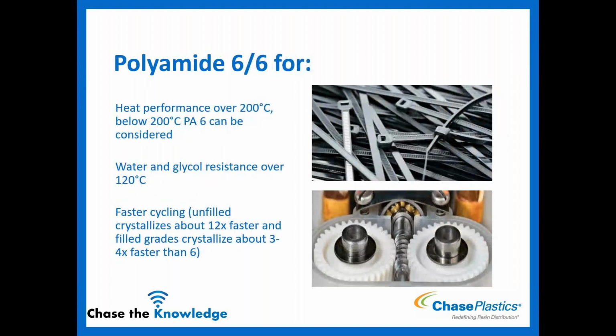Now for 6,6 being a higher temperature material, as you can expect, one of the advantages is going to be that it has a higher heat performance. If you are over 200 C, you would have to look at using the 6,6. If we go back and reference the graph that I just showed, that was a 6, fell right off at 200 C. So anything above 200 C, you have to go to a 6,6. Anything below 200 C, you might be able to consider a 6. So higher heat performance for a 6,6.